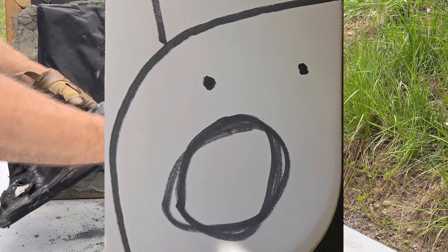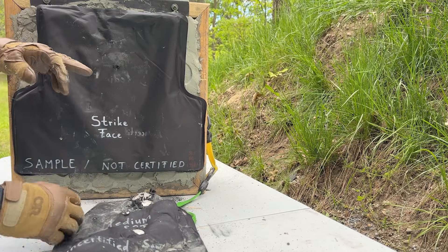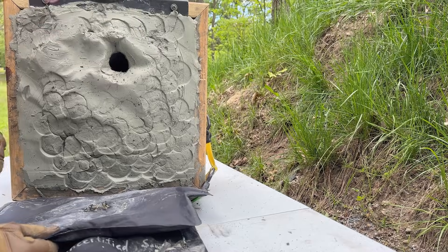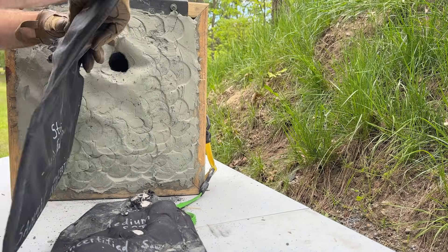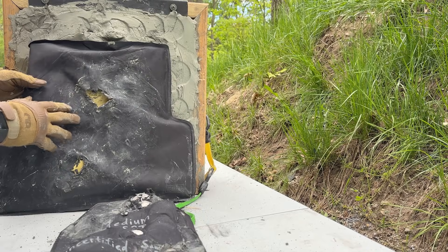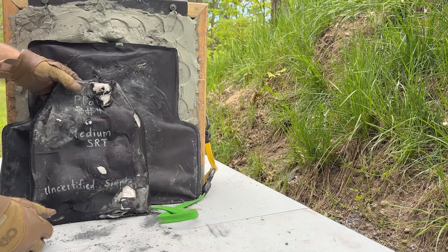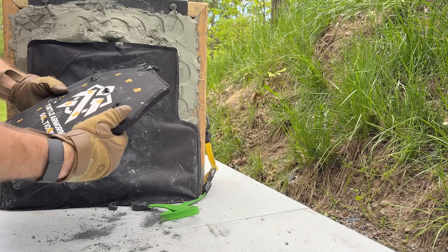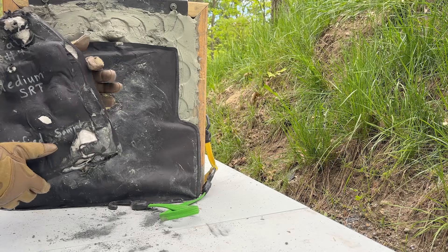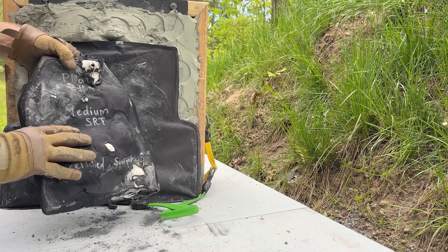We have a pass-through from our M80A1. The question is whether it passed the 3A backer or not — and yes, it did. Not sure if this is through-and-through aramid or if there are other advanced materials in there, but the ability to slow that big penetrator down is not easy to do. The M193 was contained, and there is a dimple there. At this point, we've delaminated the strike face, so sample number four is done.